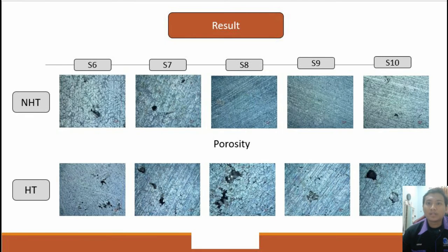The NHT is non-heat treatment and HT is heat treatment. The porosity was observed at the center of the specimen. This is because the center of the surface will contribute to the strength of the product. The porosity is studied to observe and prove the statement from the Shabestari study 2004, where she indicated that copper content exceeding 2.5% reduces the eutectic temperature, which increases the range of solidification and thus promotes the formation of porosity.